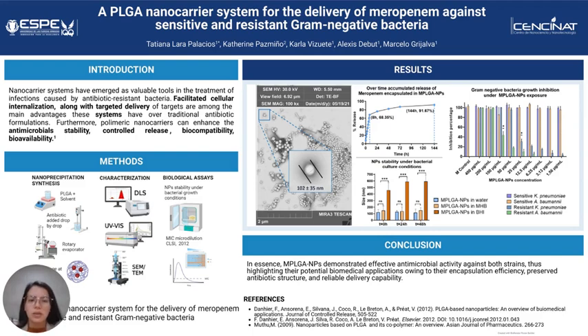Since the concentration of encapsulated meropenem within the nanoparticles correlates with the MIC values obtained using meropenem alone for both strains, our findings confirm a preserved and enhanced antibiotic activity of meropenem after 16 hours of exposure. These results are in accordance with other studies in bacterial strains using other antibiotics and carbapenems to minimize the antibiotic-resistance pattern.